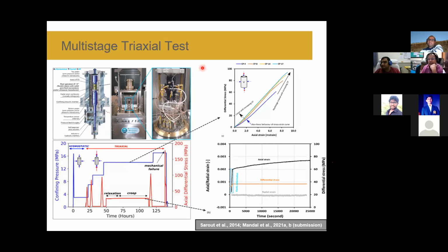It may be partially saturated, and we have not recreated any resaturation here because this kind of shale has extremely low permeability, in the nanodarcy range. To saturate it, you might need to put a sample in the lab for a couple of months, and since the sample has been exposed to air, we cannot recreate the scenario, but it can be done.